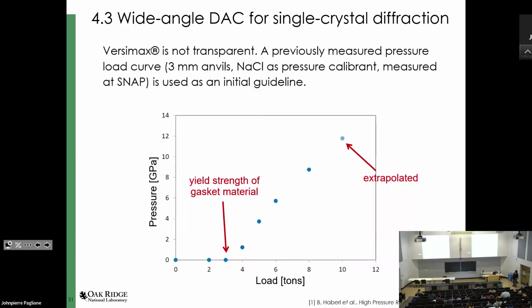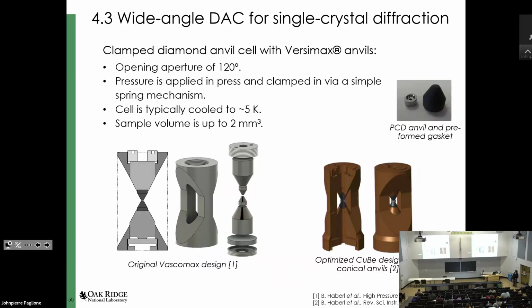The advantage is it has a very large scattering aperture. It uses Versimax anvils, so this is a polycrystalline diamond that's actually quite cheap. So you can also get it in quite larger volumes, and you can use very large gaskets to increase your sample size. So this cell also has a small spring added that adds pressure stability,